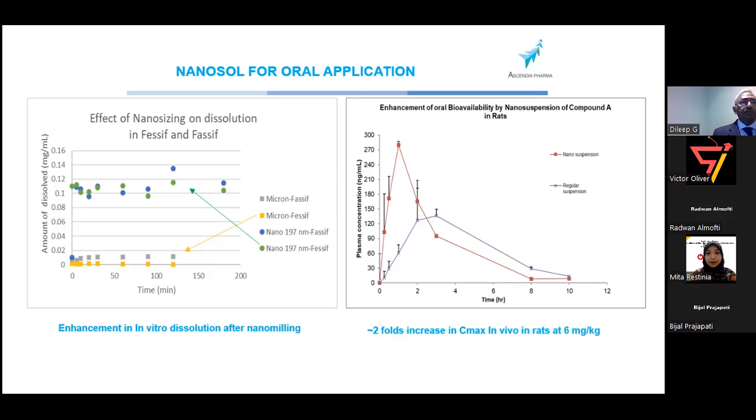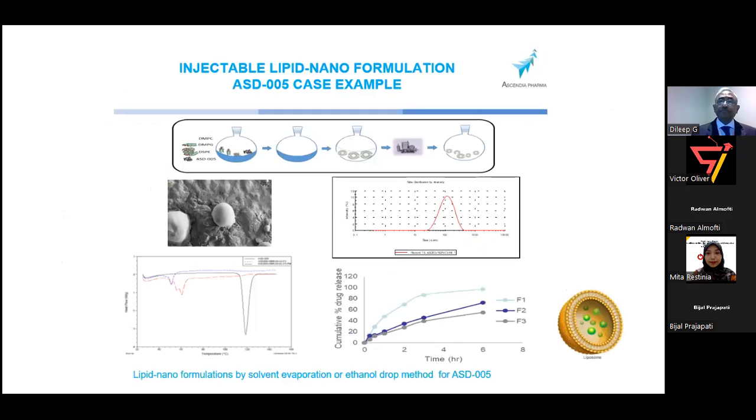We are able to really control this by changing the particle size, nano versus micron. You can see on the top is a smaller particle, it gives more exposure by reducing particle size, whereas micron size gets less exposure, right? And it's also consistent, so they can control even the food effect, which could be challenging. So this particle size reduction can also change the food effects as well. So we can go on and on. I don't have to give too many examples, but this is an example.